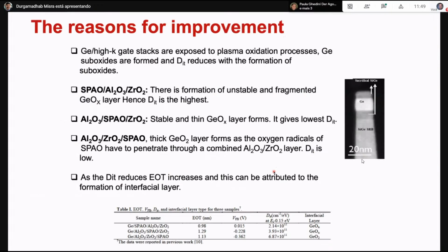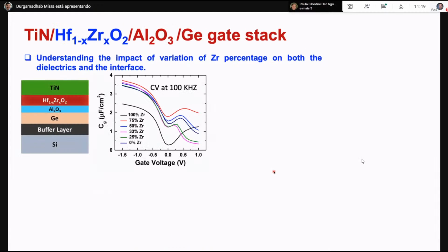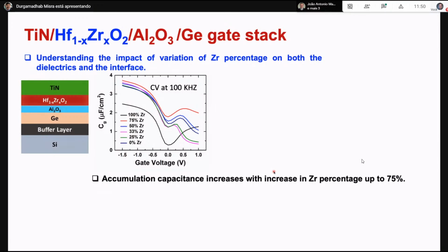Then the reason we found out is that if we do it first, before the dielectric deposition, there is an unstable and fragmented germanium oxide. But when you do it in between or after, we found this is a stable thin germanium oxide layer, and that improved the characteristics. Another issue: we also did some of these germanium gate stacks. We looked at them as a function of different percentages of zirconium, and then looked at the CV characteristics, and the accumulation capacitance increased with zirconium percentage. So we can see that the EOT will go down.